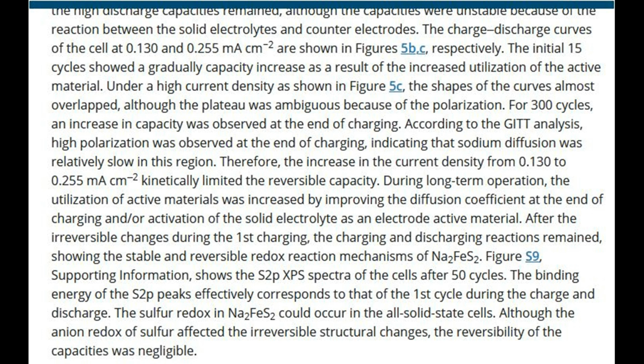After the irreversible changes during the first charging, the charging and discharging reactions remained, showing the stable and reversible redox reaction mechanisms of Na2FeS2. Figure S9, supporting information, shows the S2p-XPS spectra of the cells after 50 cycles. The binding energy of the S2p peaks effectively corresponds to that of the first cycle during the charge and discharge. The sulfur redox in Na2FeS2 could occur in the all-solid-state cells. Although the anion redox of sulfur affected the irreversible structural changes, the reversibility of the capacities was negligible.